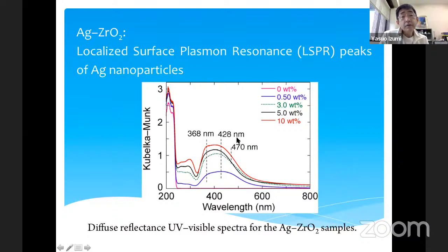So here absorption is measured depending on the amount of silver in our sample. It becomes progressively greater and reaches maybe constant around 10% silver amount in our sample. So this is characterization, and fundamentally this rising edge exists at 248 nanometers here. So this is zirconium dioxide absorption, a steep absorption. This is the semiconductor characteristic based on the characterization technique, this UV-visible technique.